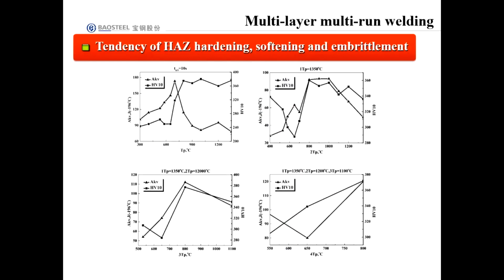This slide shows an example of multi-layer welding, which means multiple welding thermal cycles are required. Of course, it needs a well-designed temperature program if you want a better effect. Like single-run welding, the tendency of HAZ hardening, softening, and embrittlement of multi-layer welding can be obtained.